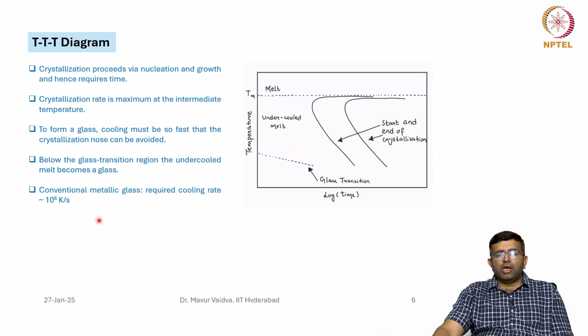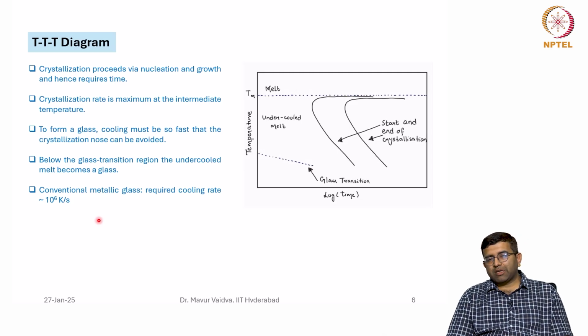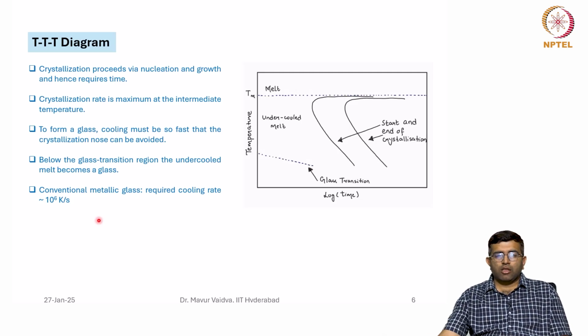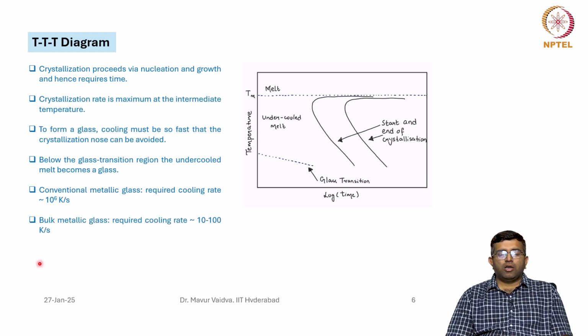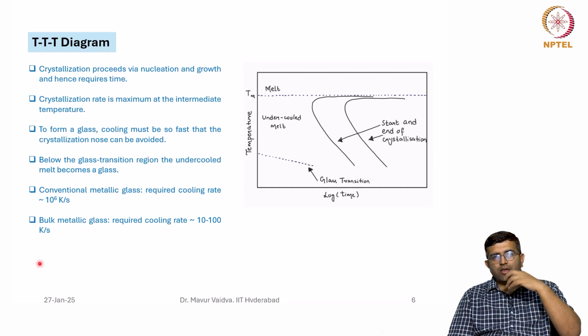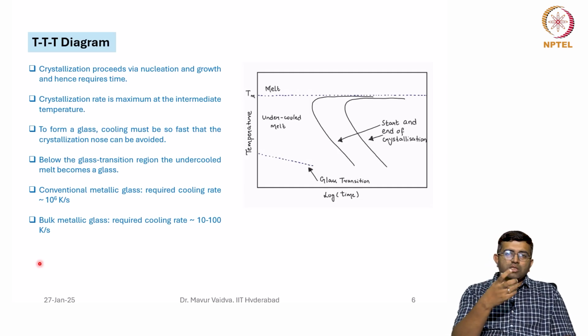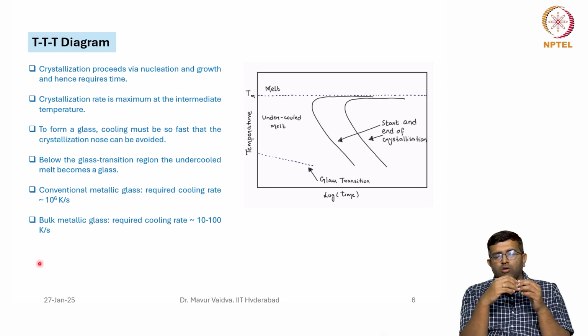Now, conventional metallic glasses require a cooling rate of the order of 10^6 kelvin per second, which is extremely high. Whereas bulk metallic glasses came later, once metallic glasses were introduced and people started working on how to make these glasses a little bigger, exploring compositions and so on. Bulk metallic glasses require a cooling rate of the order of 10 to 100 kelvin per second. Why are they called bulk? Because with such a slow cooling rate, you can also form bigger diameter glassy rods or ribbons and so on.